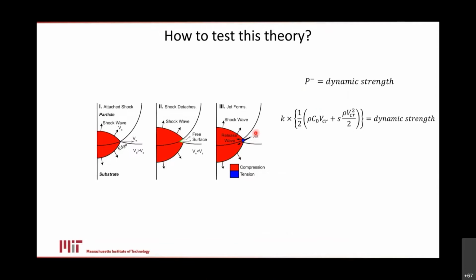So why don't we go quantitatively work on this and see if we can't convince ourselves that this really is a hydrodynamic phenomenon. So here's the way we've approached it. I'm a big fan of scaling laws because they capture essential physics in sort of a beautiful way. And so what we did is we developed a scaling law. What we said is, okay, look, the jet phenomenon here, this basically happens if we flip a shock wave into tension, and if that induced tension exceeds the local strength, that's when a jet is going to shoot out. So you can write down an expression for the dynamic pressure. This is just a straightforward textbook expression where the velocity goes in there and the density and the speed of sound and so on. But this is the pressure you produce upon impact. You flip that into tension, and so there's some proportionality constant you don't know, but anyway, it's just some constant, so we'll flip it and we'll leave it in there.